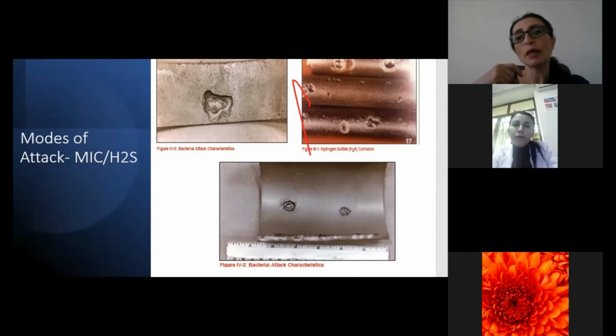You see from this photo a double ring, pins like a double ring. It means that this is pitting with a flat bottom, and the top ring is bigger in diameter, and then you see a smaller bottom. That's why from the top surface you see a double ring. And usually pittings of MIC have a flat bottom. But again, I want to repeat that this is not the only sign of MIC. I know from my experience, a few times I saw a photo, even saw the metal, and I was sure this was MIC, but the bacteria results showed no bacteria. So we can't rely on the morphology to define the corrosion type.